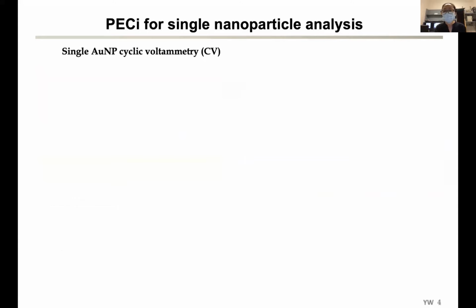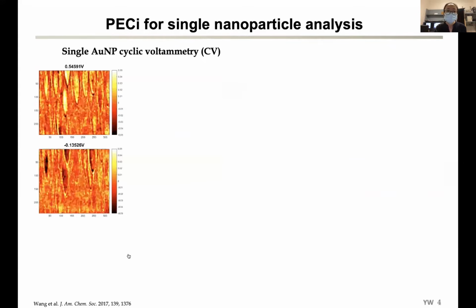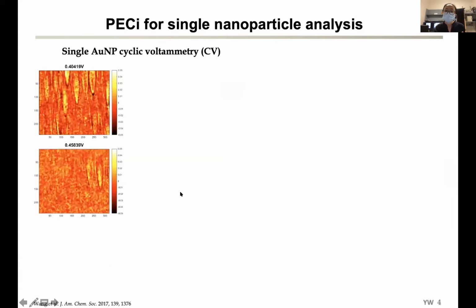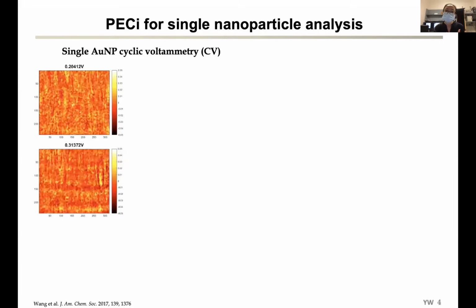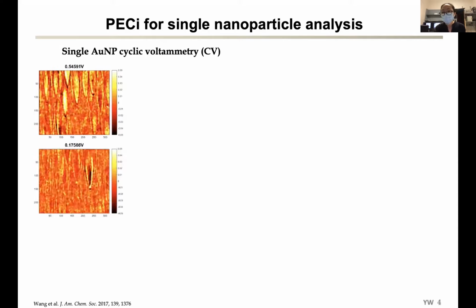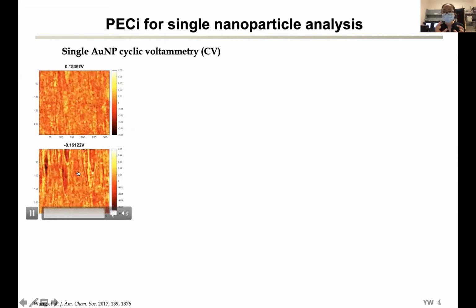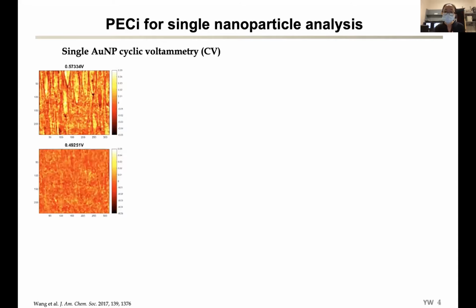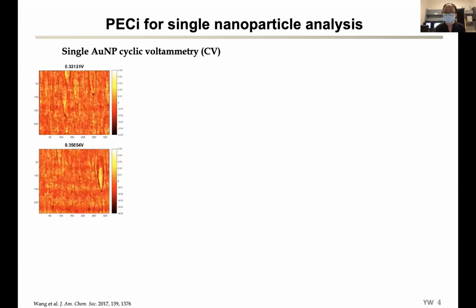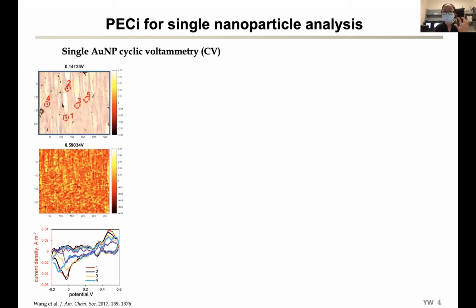The first one is we would like to use this plasmonic-based electrochemical imaging technique for studying single nanoparticles. We have previously worked on demonstrating the capability of getting cyclic voltammetry at the individual nanoparticle level. So here those two are videos showing that you can monitor the electrochemical changes at individual nanoparticles. And if you extract the signal from each tail of the nanoparticle, you can get the single nanoparticle CV.